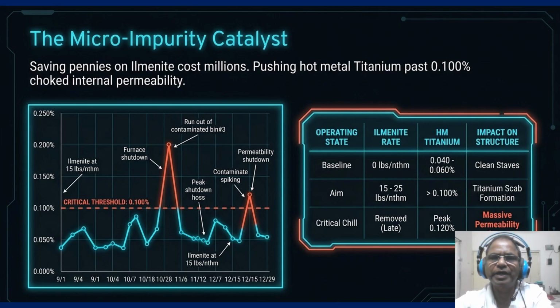But look at that spike in November. We pushed titanium past the critical threshold of 0.10%. The table highlights the result: massive permeability loss. The so what is the formation of titania scab that acts like a bottleneck in the stack.